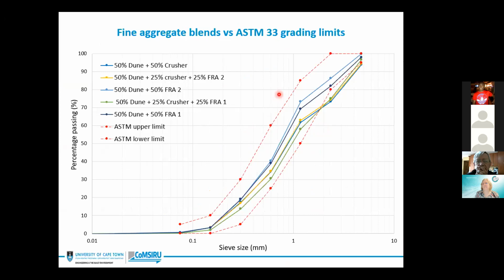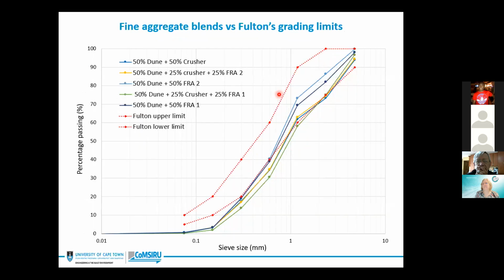Here is a sieve analysis of the blended recycled fine aggregates. And this was checked against the ASTM C33 grading limits. And we can see that the materials generally fit within the ASTM limits. We also checked them against the grading limits that were stipulated in Fulton's textbook. It is observed that the aggregates do not entirely fit in here. This is because the Fulton limit is narrower and has a finer grading than the ASTM limits.